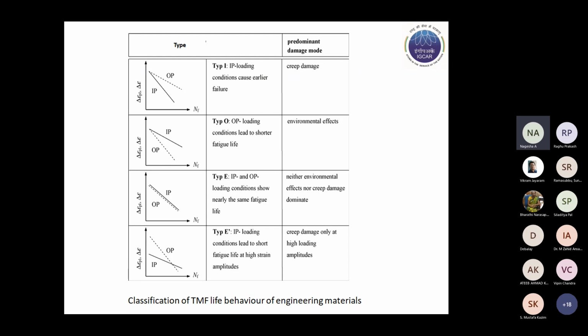And I have told that IP and OP are the most basic and most normally investigated waveforms under TMF. Depending on how the life variation happens between IP and OP, there are different types, mainly some 3-4 types. Type I, wherein IP or in-phase loading gives rise to lower cyclic lifetimes compared to OP. The predominant damage here is creep, because maximum temperature coincides with the peak tensile strain. So when creep damage becomes more prominent, this kind of situation happens where IP loading gives rise to a lower cyclic life compared to OP.